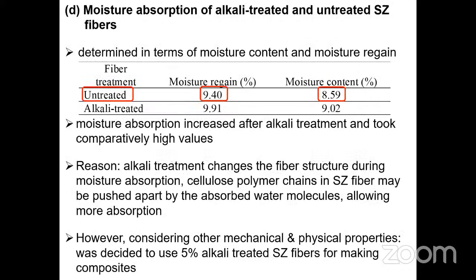In this slide, you can see the moisture absorbency of alkali treated and untreated Sansevieria fibers. Moisture absorption increased after alkali treatment and took comparatively high values. Alkali treatment changed the fiber structure during moisture absorption. Cellulose polymer chains in Sansevieria zeylanica fiber may be pushed apart by the absorbed water molecules, allowing more absorption.